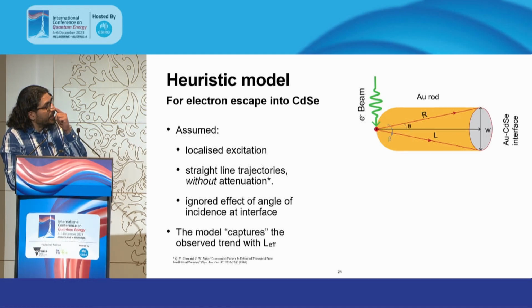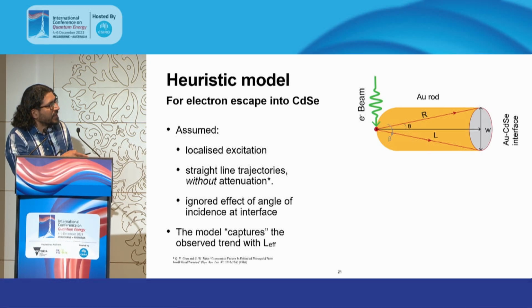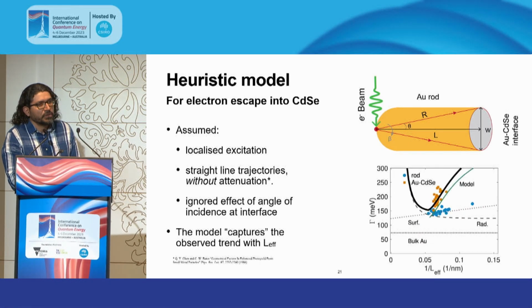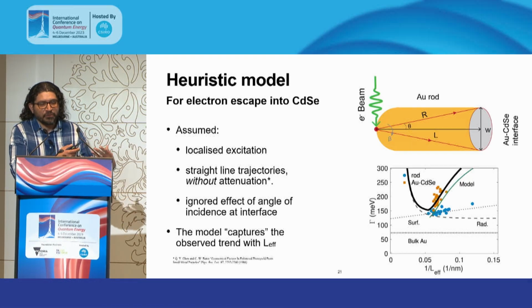To model this, what we did was to think of the whole process like a random pool game where we come in with the white ball and we kick an electron from the tip of the rod. When we park the electron beam here, we kick an electron out, and we count, as a function of this escape cone, what is the probability that this electron will reach the surface. There are a number of other approximations we have done. This is just to see if this is similar to reality. And by just doing this geometrical analysis, we get a model that nicely reproduces the data. Not only is this satisfying, but the model depends on the geometry of the particle and is giving us further insight into how to make the particles that best result in the conversion of photons to electrons.